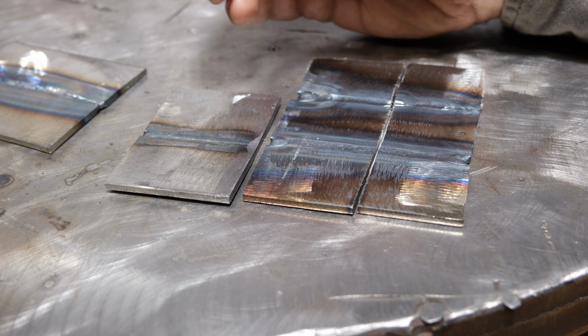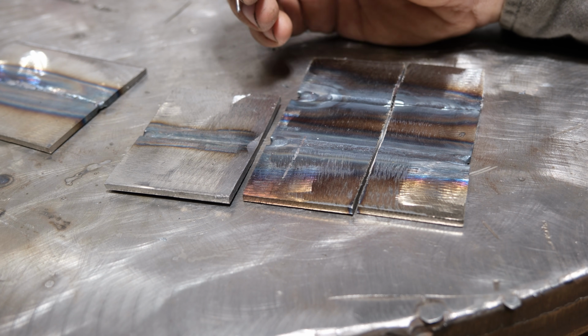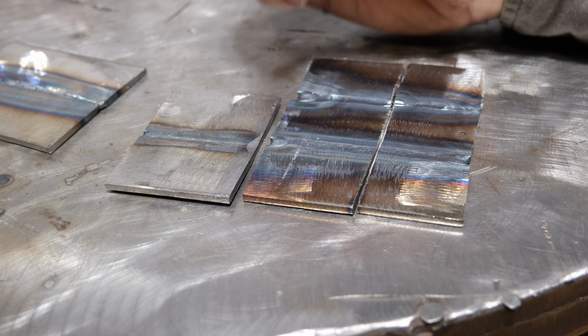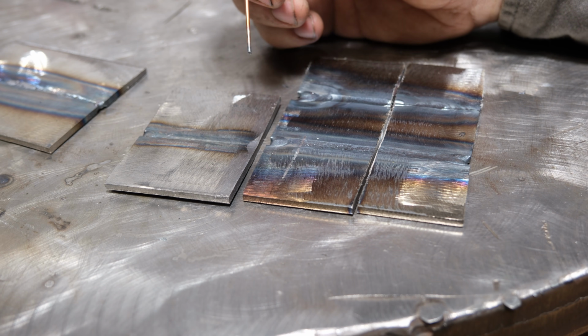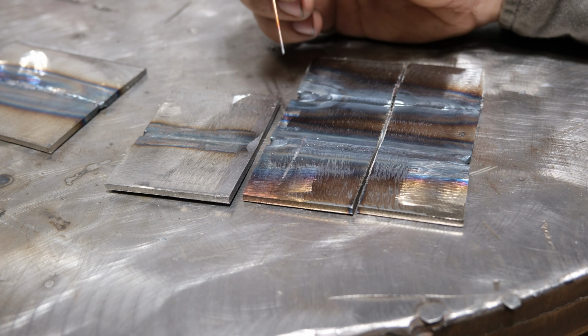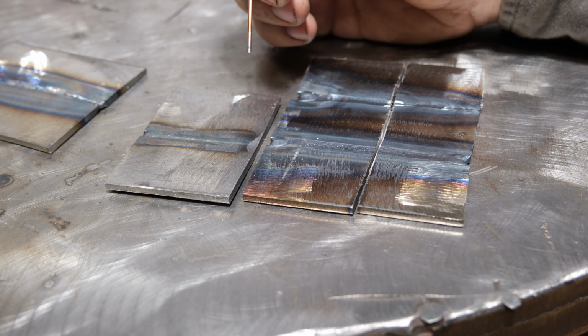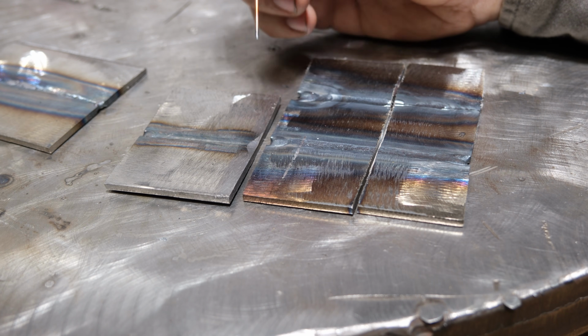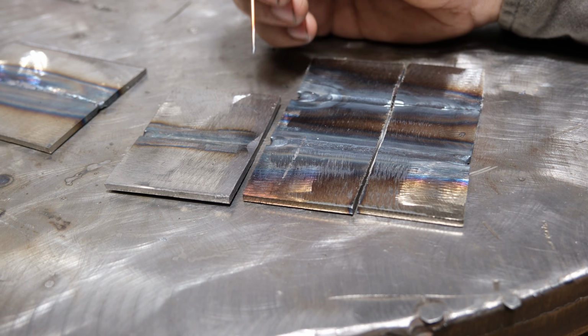So I see that as a detriment by trying to use the plate itself as filler, especially if you happen to weld something like tool steel or any number of higher strength alloys. If you do not use filler and just try and melt the base material onto itself or use it as filler, you will suffer from cracks of that weld, guaranteed. So filler is generally better than no filler, especially on higher strength alloys.